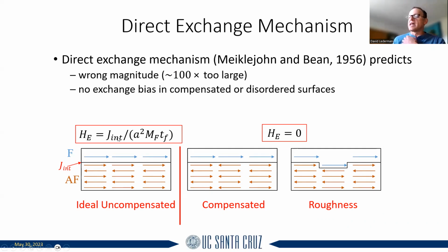It would have to be equal to something like the exchange interaction per unit area, and this is the area of a unit cell. This is the magnetization, and this would be the thickness of the film. Because it's an interface interaction, the thickness of the ferromagnetic film matters. Technically, if the film is very, very thick, the exchange bias will be less because it's less affected by the surface. But there are several problems with this.